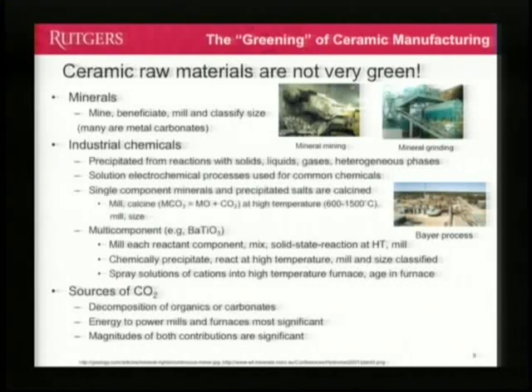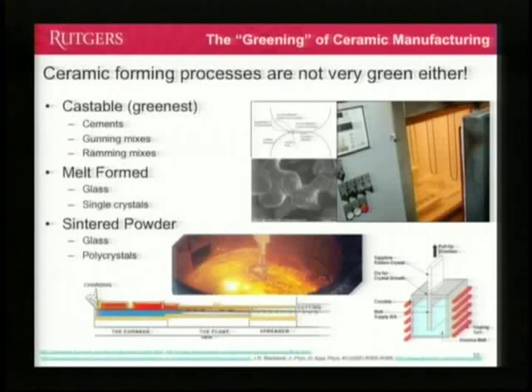We can choose to cast it, which means we're going to mix it with water and spray it. Sometimes this spraying stuff isn't such low temperature. Here's a gunning mix that's actually sprayed at a very high temperature, around the temperature that steel is made. These ramming mixes are actually ones that don't require high temperatures, but they're usually used for high temperature furnaces to fire other things, and they rely on the hardening at that high temperature to give it its high strength. Glasses and single crystals are made by melt-based processes, quite elaborate, quite energy-consuming. If you're not going to melt, then you're going to go right some fraction of the melting temperature and either work with glass or polycrystalline materials, and either way, you're just spending a lot of energy doing all this stuff.